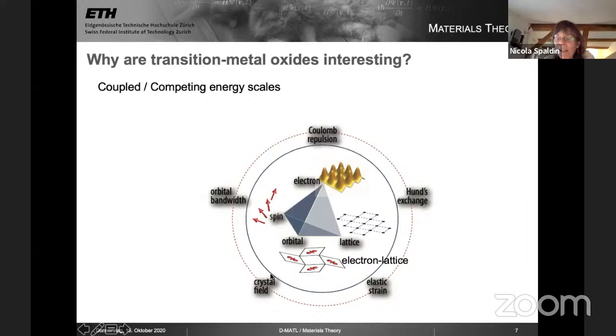Crystal field splittings, the interaction between the oxygen ions and the energy levels in the atom, are also of a similar energy level. Strain energies that can occur in the lattice through spontaneous internal distortions or from external perturbations are also the same energy scale. And the Hund's exchange, the tendency of the electrons to align their spins parallel, can also be of a similar energy scale. And so all of these interactions between electronic, spin, orbital and lattice contributions are very similar, which leads to a very strong tunability, sensitivity of